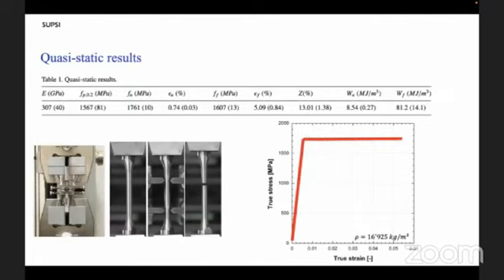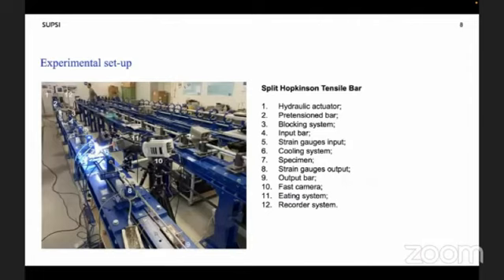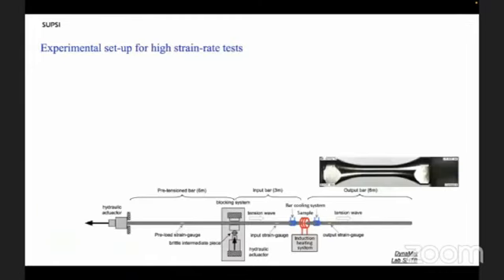this alloy. The dynamic response of this commercial tungsten alloy at high strain rate was investigated by using a split Hopkinson tensile bar installed in our laboratory, as shown in this slide. It consists of two straight circular bars with a diameter of 10 millimeter and lengths of 9 and 6 meter. The first 6 meter of the longer bar is used as a pretensioned bar, while the remaining 3 meter is used as input bar. The second bar serves as an output bar. The tungsten alloy specimen is screwed into the input and output bars.